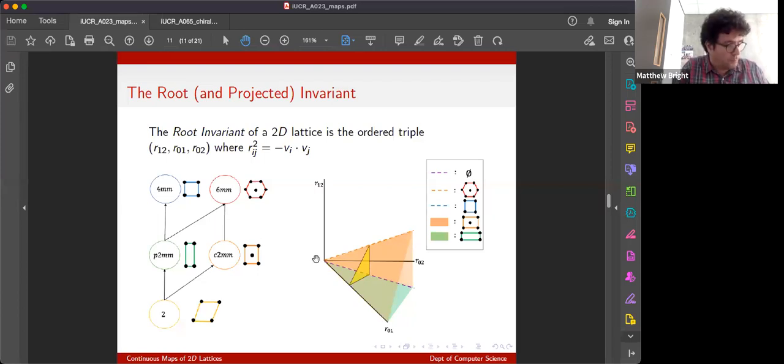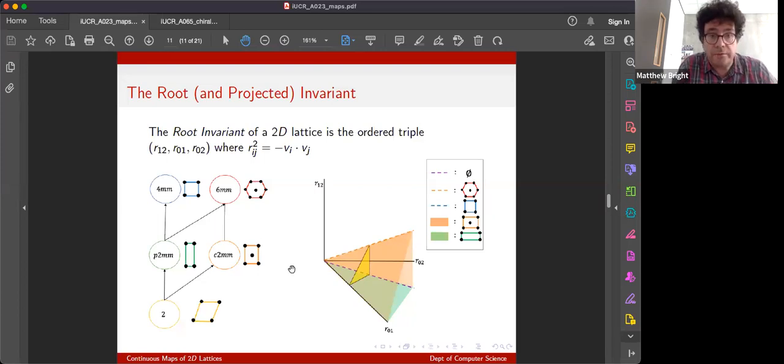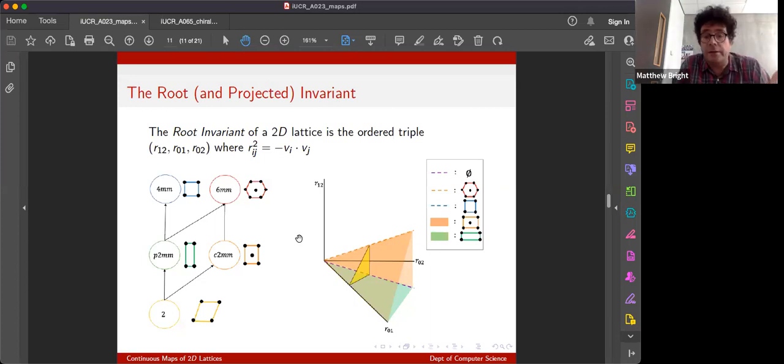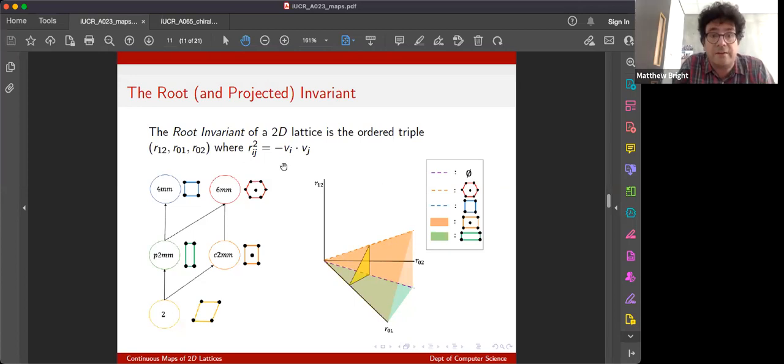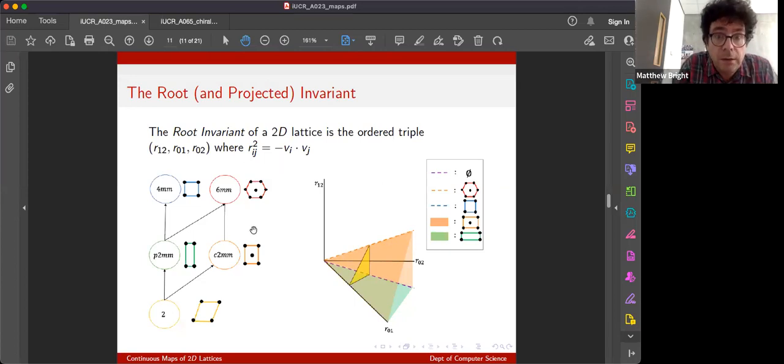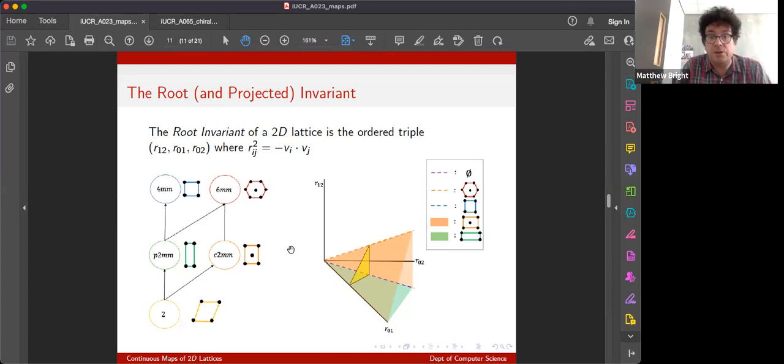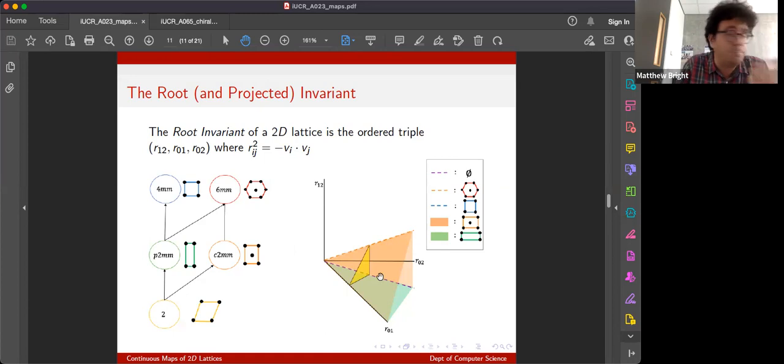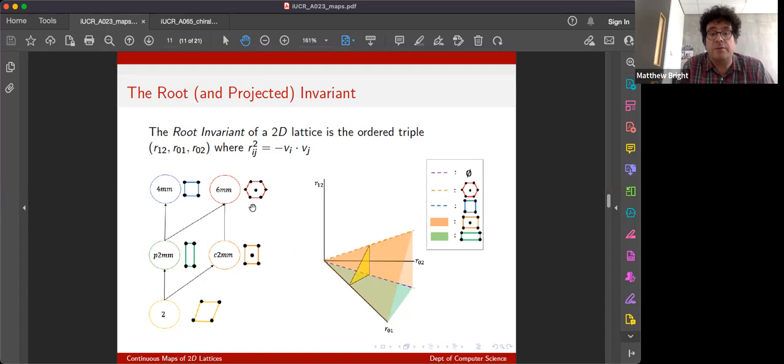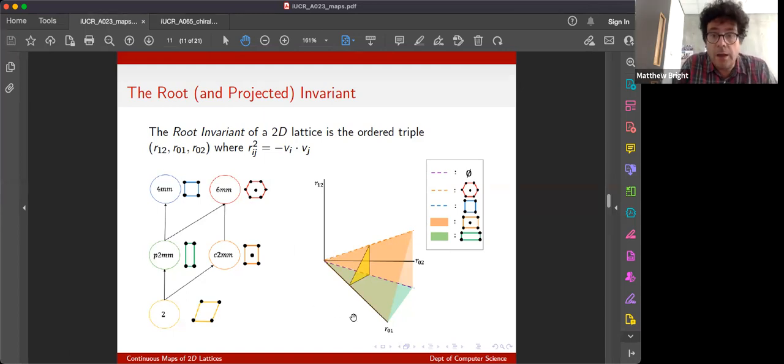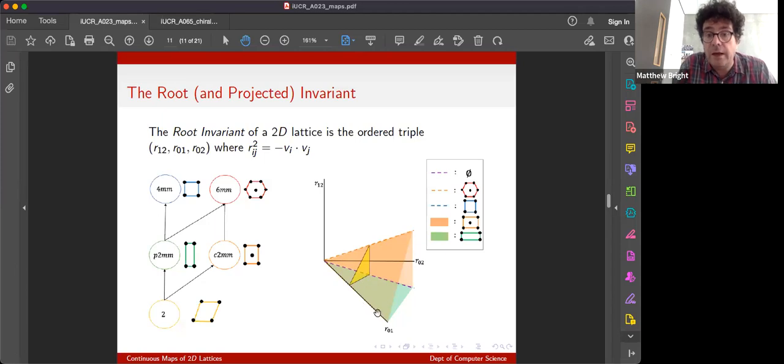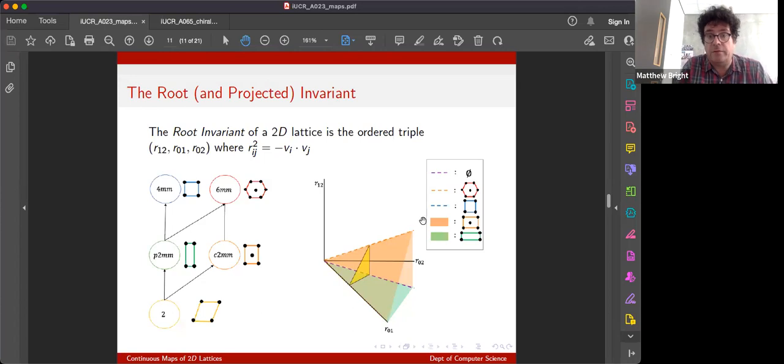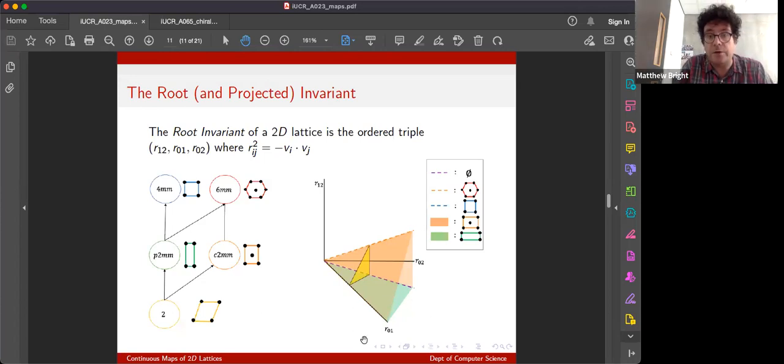And that gives us our root form, no more or no less than these pairwise ordered inner products. And the fact that it's a complete invariant means that not only is every lattice mapped to an ordered triple, but that any ordered triple maps back to a lattice, uniquely. We can uniquely describe them in two ways. So we have our space, it gives you a space for free, in fact a cone in three dimensions. And even better, the discrete classification that we understand from the cone falls out nicely as subspaces of the space of lattices, the intersection of various planes in three dimensions with the cone.